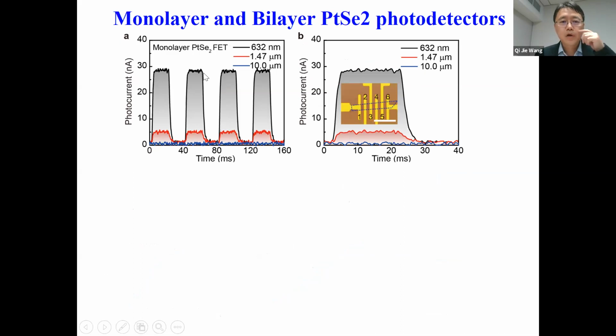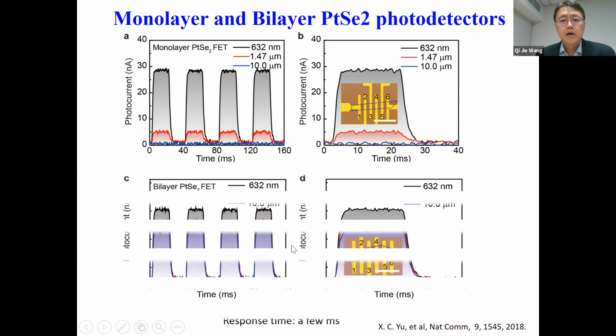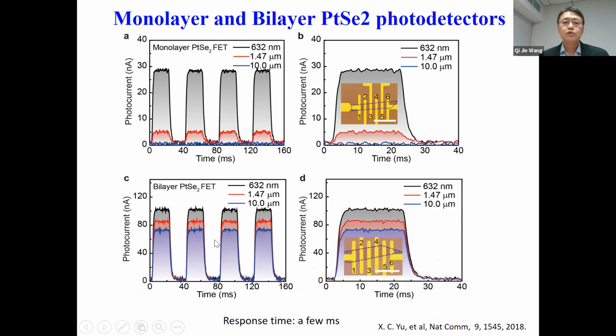As expected, the monolayer PtSe2 detector has a large photo response in the visible and some response in the near infrared. However, because of the large bandgap, we don't see any photo response under mid-infrared light illumination at 10 micron. On the contrary, if we use bilayer PtSe2 to build this FET device, we see a significant response in both the visible and up to the mid-infrared region.